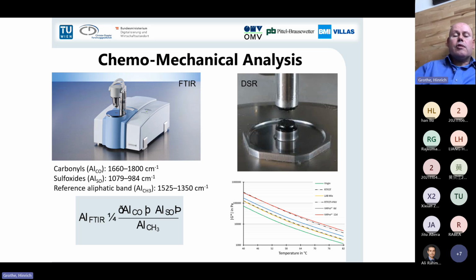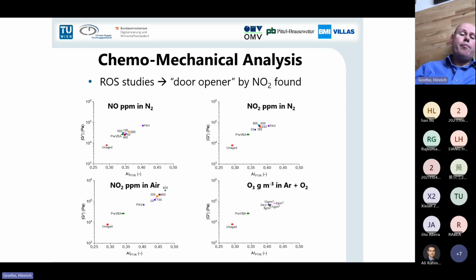And then we tried to correlate that with mechanical investigations, with rheology. So that's a DSR. So we can take DSR measurements and correlate that with infrared. And okay, sorry, here we have obviously a little problem, but we can calculate an aging index. That means we take the infrared bands, we are integrating those infrared bands and set a correlation between the oxidized, that means the carbonyl bands, and the sum of carbonyls and sulfoxides in relation to the absorption of the methyl band, which is not changing so much during aging. And this aging index we have plotted here with the G star value from the DSR, so the DSR against the aging index. And what can we observe?